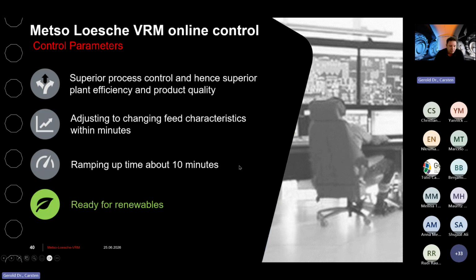And it's ready for renewables. We touched on that because it's so flexible. You can utilize that if you have less power available, for example, because you have a cloud bench. All you got to do is set your feeding parameters, adjust your grinding pressure accordingly, change your classifier, and you can work with the existing amount of energy always in an optimum range. So you don't have to shut down the mill, but you could even do so.